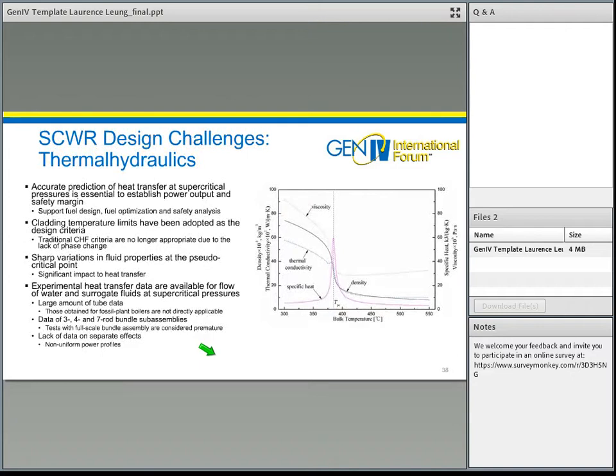So for thermohydraulics, one of the key differences between the SCWR and the current fleet of reactors is the lack of phase change, because at supercritical pressure the coolant acts as a single phase. There's no boiling, so no phase change. So the traditional CHF criteria, or critical heat flux criteria, are no longer valid or appropriate for the SCWR.